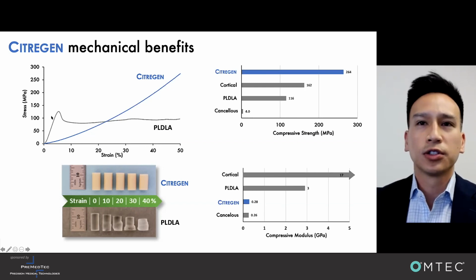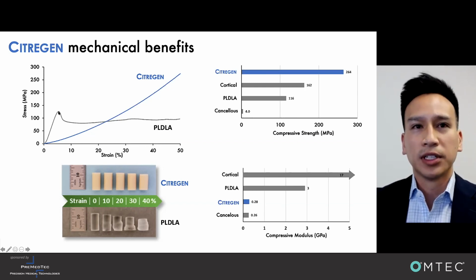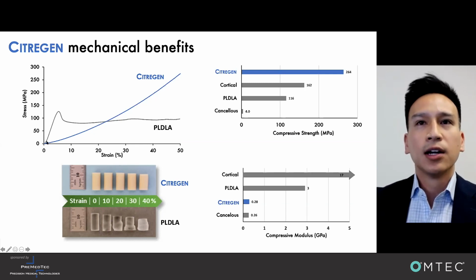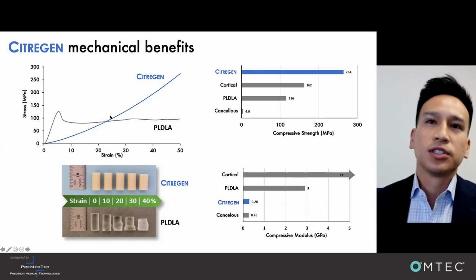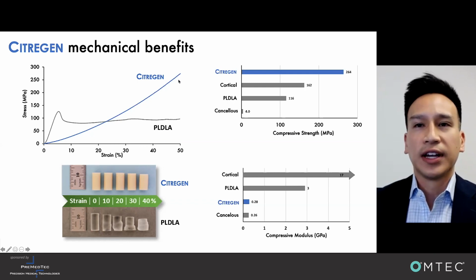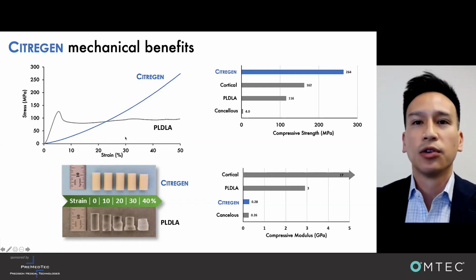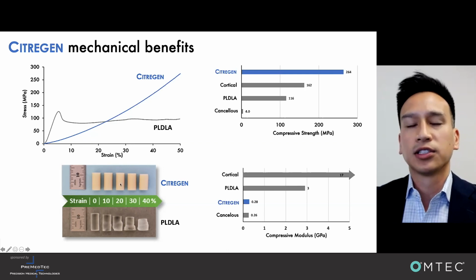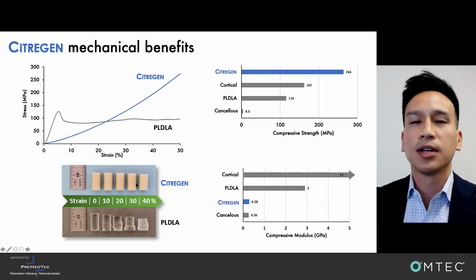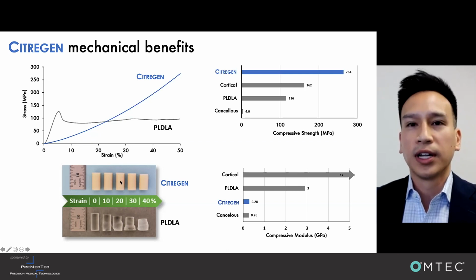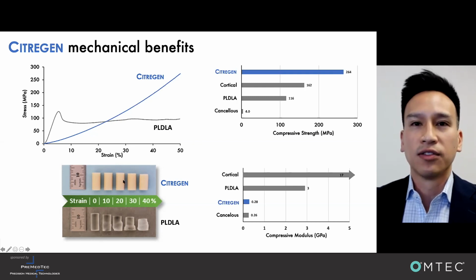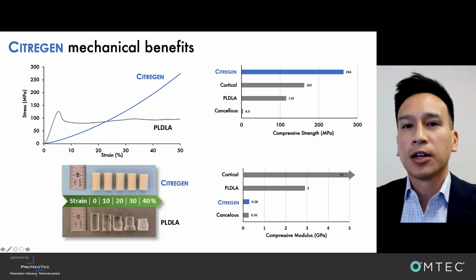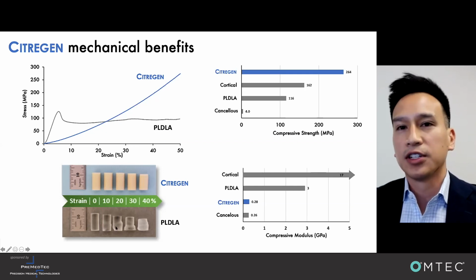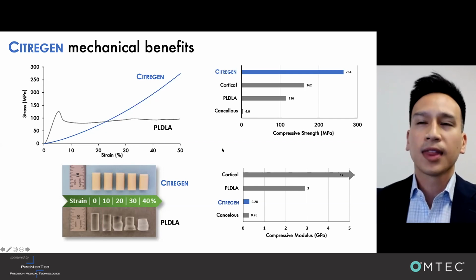You can notice that traditional thermoplastics begin to yield and permanently deform under 10% strain, whereas Citregen is an elastomer, so there is no plastic deformation and it just fails up to about 50% strain. Now this is loaded with up to 60% ceramic. So it has a high ceramic content and still maintains elasticity. Looking at the pictures on the bottom, you can see the Citregen material on top, where it can be compressed up to about 20, almost 30% strain and recover without permanent deformation. In comparison, you can see the PLDLA on the bottom, and after 10% strain, it starts to permanently deform.